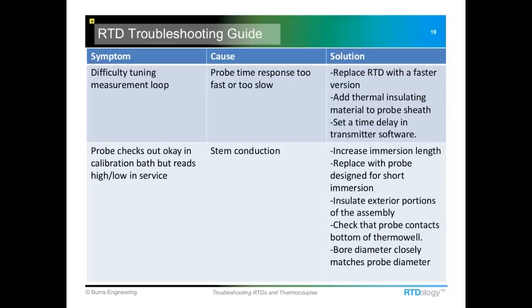Other areas, and this gets back to the question we had about the length of an RTD. You've noticed a temperature error in your process. You take the probe out, we check it in an ice bath, it's perfect. It shows no problems. The insulation resistance is fine. But you stick it back into the service, and it's either reading too high or too low. And this is a real indication of stem conduction. What's happening is that while it's in the process, the ambient conditions are affecting the temperature that the sensor is seeing.